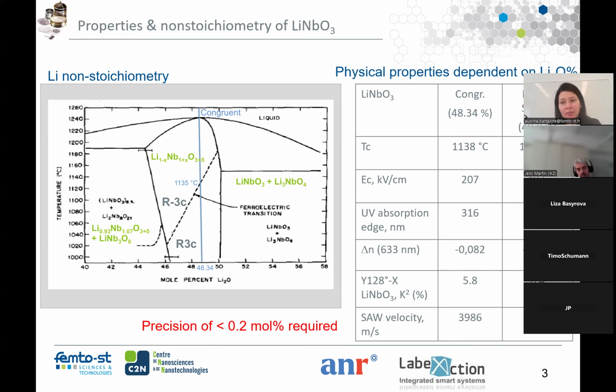And sometimes in the smart cut films, the lithium concentration is even a little bit lower than it was in the congruent crystal. It depends on the process which was done, and if a film lost lithium during diffusion, for example, into the silicon dioxide, and so on. So this phase exists in a very broad range, from 46.5 mole % to 50 mole %, and the properties of lithium niobate are highly dependent on lithium composition. If we take some examples, which might be interesting, let's say for the HINA project, like the coercive field, it changes by several times if you change your concentration from congruent composition to nearly stoichiometric one, so you change about 1.5 mole percent.